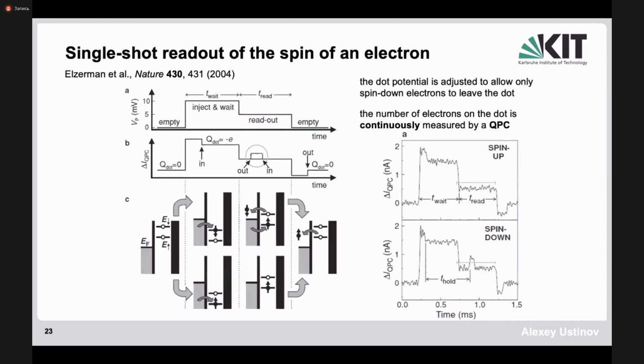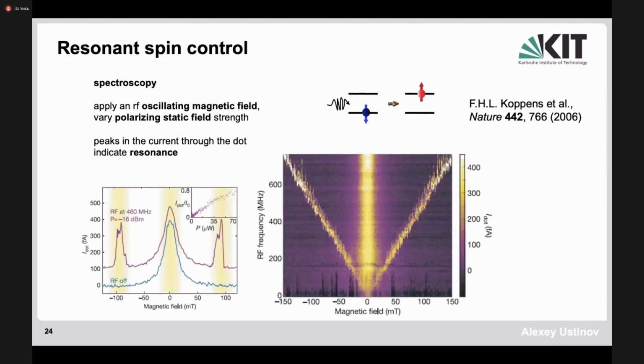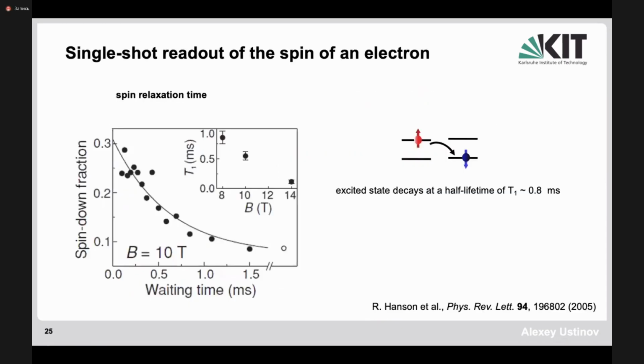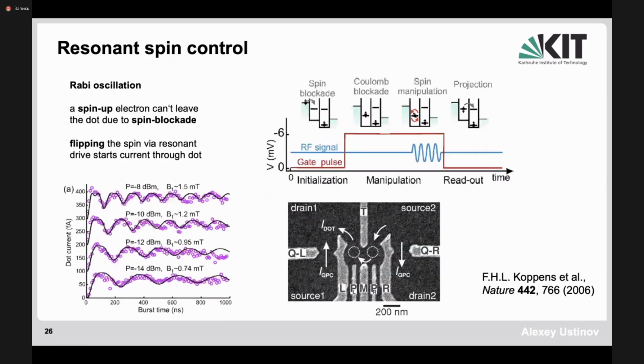Skipping the details, basically this is what was observed in this experiment many years ago: the electron going from spin up to spin down state was split by the Zeeman energy, and then by applying short pulses, people were able to measure not only spectroscopy but also Rabi oscillations of the electron in this double dot, and also to measure the spin relaxation time, which turned out to be quite appreciable, in the range of milliseconds at low temperatures. And this shows the resonant spin control. When you increase the amplitude of the AC signal, these are Rabi oscillations. As you see, the frequency is changing here. So again, we talk here about Rabi flopping between 2 states and then measuring the projection on the individual state of the dot.